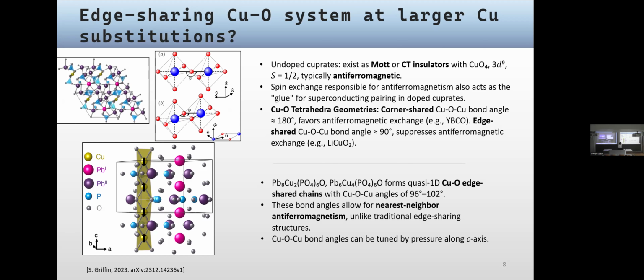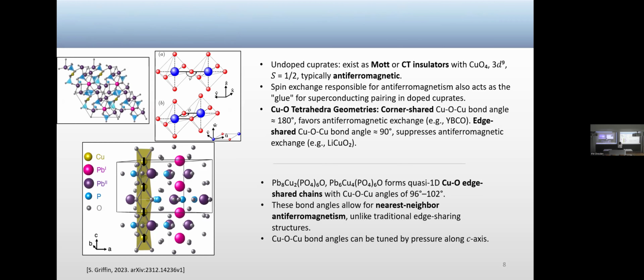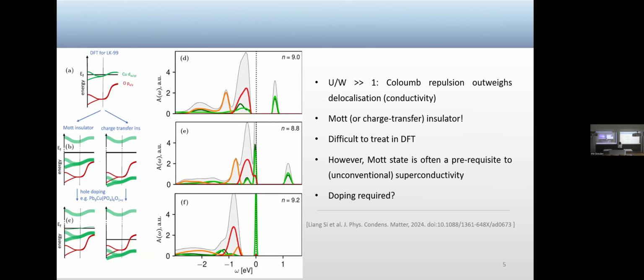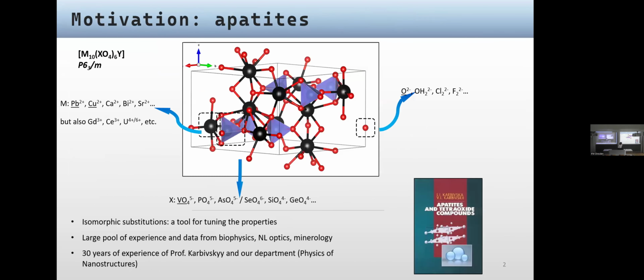So still, I would say, not much if we take the whole unit cell, which is 41 atoms. But in terms of replacement, it replaces one of the lead positions, and there are only 10 per unit cell. So it's visible. It's pretty visible in the density of states too. It's not that it's 1 per 1,000 or something. It's still there.